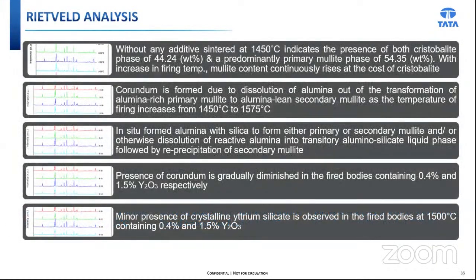In the Rietveld analysis, basically without any additive sintered at 1450 degrees centigrade, the presence of cristobalite phase of 44.24% is observed, and a predominant primary mullite phase of 54.35% is observed. With increase in firing temperature, mullite content continuously rises at the cost of cristobalite. So initially cristobalite forms, but later it disappears and mullite formation starts.